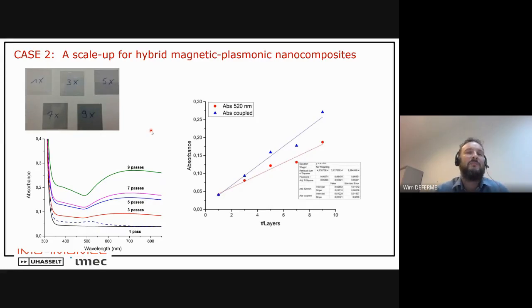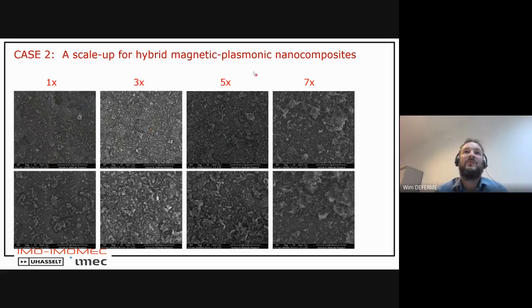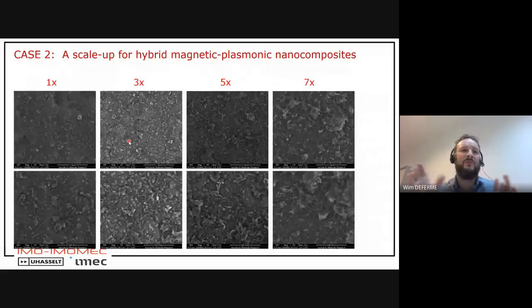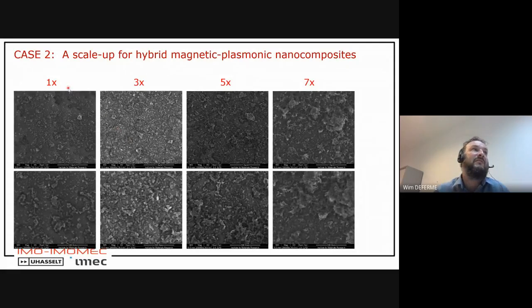So this is another representation of the redshift we see. And then on top of this gold, we put the magnetic nanoparticles, which in this case is the silver. And of course, what the people in Leuven did in synthesizing is putting ligands on the nanoparticles such that the silver can only bind to the gold and not to the substrate. And that means you can only have the same coverage as you had in the beginning with gold. So for example, if we have 5 times gold and we put several layers of silver